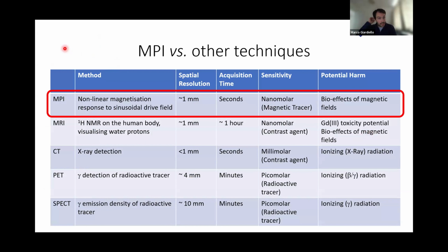In terms of MPI versus other techniques, I've just put a few up there. So MPI, this is MPI at the top. It works by the nonlinear magnetization response to the sinusoidal drive field. It has a spatial resolution at the moment of about 1 millimeter. The acquisition time can be quite fast. And because there is no magnetic material in the body, there is no background, so it can detect quite low concentrations of that tracer. There's limited harm to the body.